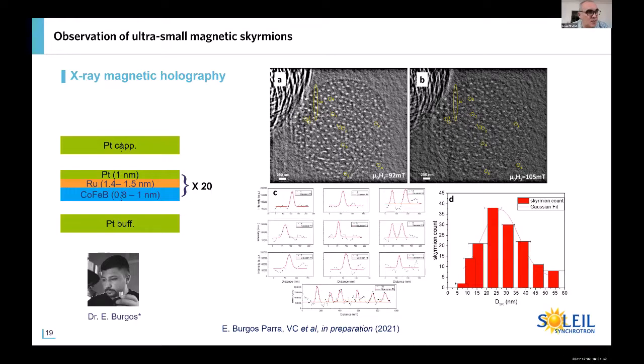Yeah, the ruthenium. What you need is to have two different materials, because if you have symmetric elements around the magnetic layer, then you have no chiral interaction, and so you cannot stabilize those skyrmions. Ruthenium instead of other ones is because, at least in our sputtering machine, we succeeded to optimize the system. This is the same that is used for the synthetic antiferromagnets, to get very good values, the quality of the films, the quality of the interfaces, and the fact that we do have a sizable DMI interaction coming from this cobalt iron boron ruthenium interface.